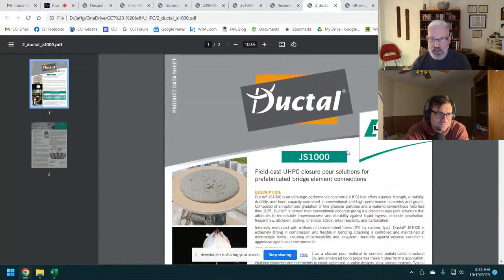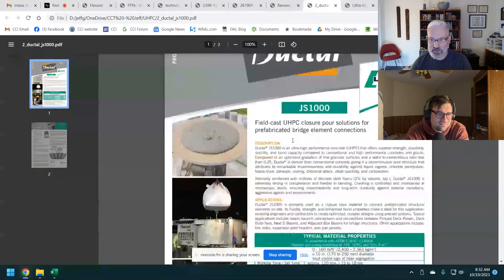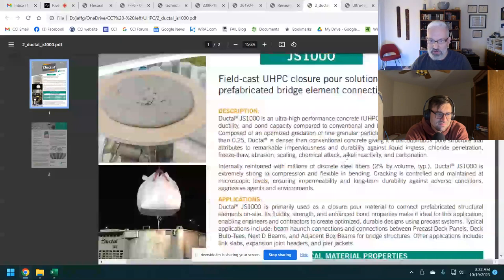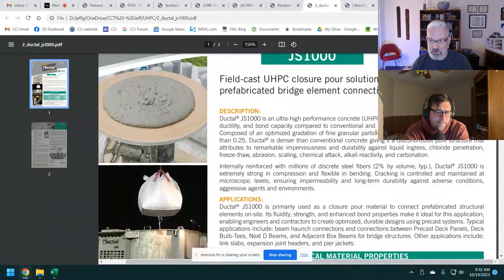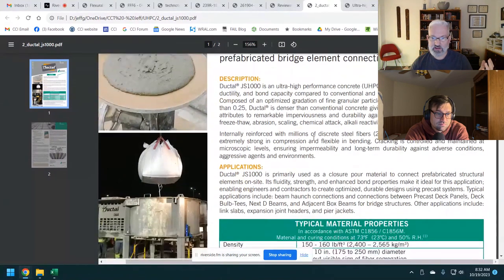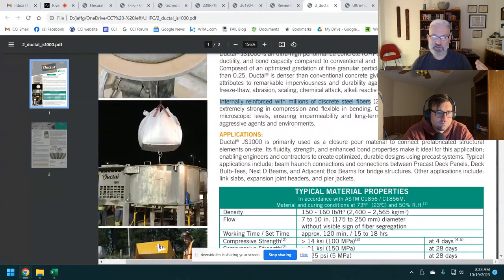I just pulled this up offline, and you know, UHPC, all that. I'm going to zoom in a little bit. And the point of this is a low water cement ratio, below 0.25. Now that's not a rule. Sometimes it's below 0.27, sometimes below 0.20. I've seen mix designs that use a water cement ratio of 0.15, incredibly low. Right here, steel fibers. Not glass fibers, not PVA fibers, steel fibers. Now, there are some UHPC mixes that do use PVA fibers, which are basically used for architectural reasons, like what we do. They have a lower compressive strength and a lower flexural strength. So it's a subset of UHPC.